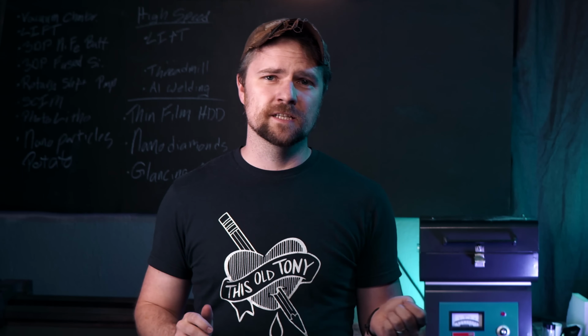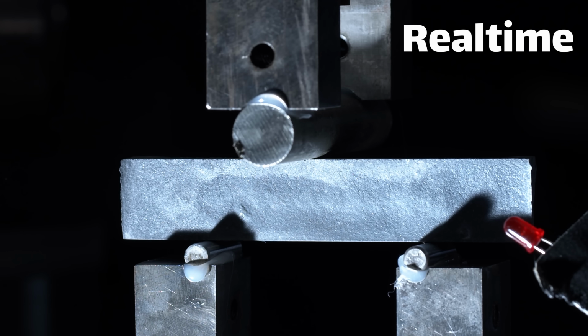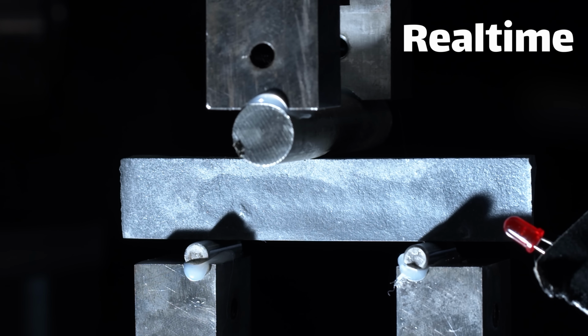The paper didn't do this, but I was really curious about the mechanical properties, and I felt like that would be a really good test to see if this actually did anything. Like, did the material become stronger or more ceramic-like than before it was fired? So I set up a 3-point bending test and ran an unfired sample first, and you can see that it doesn't really behave like a ceramic at all.